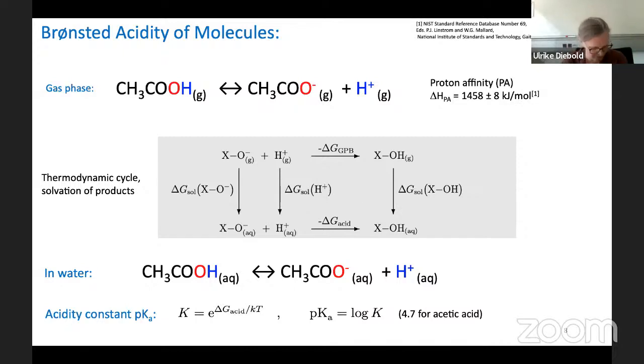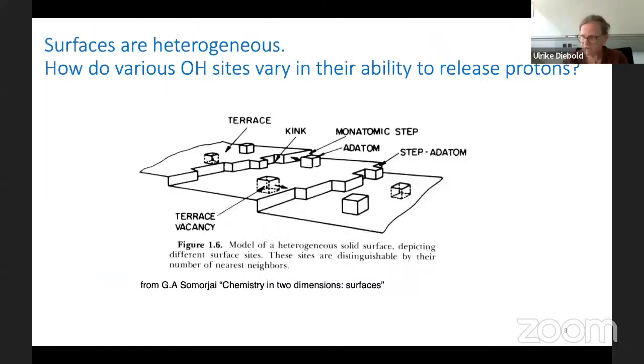Now, since the first part of my talk is strictly in ultra-high vacuum, we really have no handle on this lower part, but we have a handle on this other part. And I think even this upper part, how easy it is to remove this proton, the proton affinity, is quite relevant for oxide surfaces. And the reason is, for a molecule, of course, it's one proton that you can get off, or maybe two, but surfaces, any surface, especially oxides, are very heterogeneous, right? So you have first of all many different possible places where atoms are. They have terraces and kinks, and they have adatoms and vacancies and dopants and all those things. So because surfaces are heterogeneous, and this is an oxide surface, these hydroxyls, depending on where they sit, can give off this proton much more easily or not.